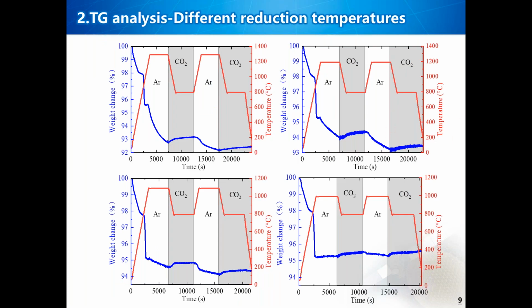So then, based on the next analysis of different content on the thermochemical cycle performance, copper oxide and nickel ferrite was screened and identified as the optimal dopant among the studied materials. Copper oxide is decomposed at from 800 to 900 degrees, so the oxidation temperature is 800. So to ensure the reaction rate and feasibility, for further discussion, the appropriate reduction temperature will be discussed and selected.